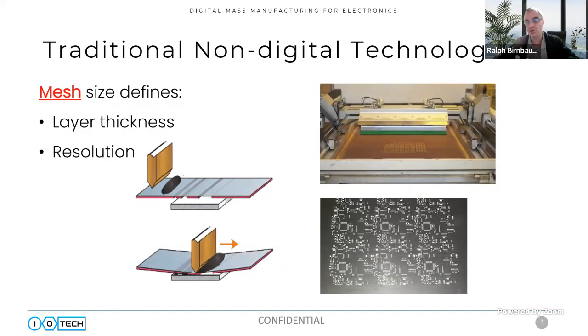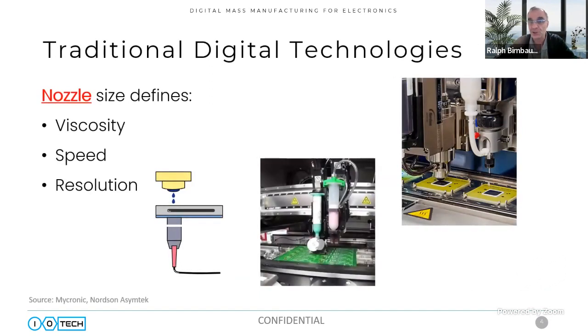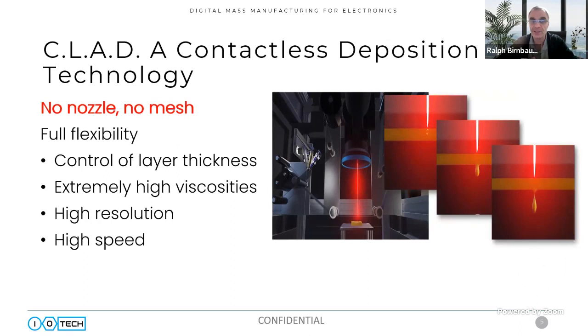So traditionally, you have non-digital technologies, for example, screen printing, where there's some kind of mesh which imposes a constraint on the layer thickness as well as on the resolution of the design. Traditional digital technologies will often have a nozzle, where the nozzle imposes a constraint on such things as the viscosity of the material, because if it's too viscous, it'll block the nozzle. The speed, the nozzle needs to be moved around mechanically, and also the resolution. In continuous laser-assisted deposition, which is a contactless technology, there's no nozzle and there's no mesh, which removes those constraints, giving you full flexibility. So we can control the thickness of each layer. We can print materials of extremely high viscosities. And of course, we do that at very high resolution and basically the speed of the laser.